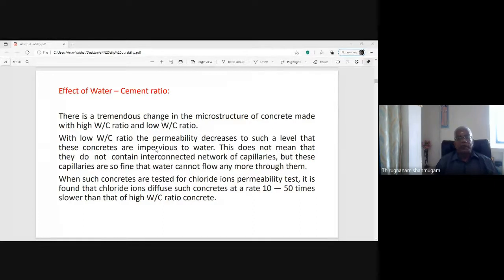Effect of water cement ratio. There is a tremendous change in the microstructure of concrete made with higher water cement ratio and low water cement ratio. Nowadays, SEM, scanning electron microscope pictures are available. They show the microstructure of the concrete elements. Thus, we will examine the microstructure with higher water cement ratio and lower water cement ratio. With a lower water cement ratio, the CSH gel is completely formed. It reduces the voids in between the aggregates and other things. Capillary pores are very, very few. So it has higher durability when a lower water cement ratio is used.